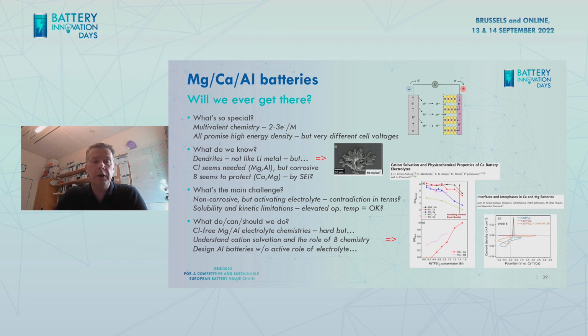One hobby horse of mine when it comes to aluminium batteries is that aluminium batteries is one thing, aluminium ion batteries is something else. So if you're going to use, let's say, graphite, where you intercalate AlCl4, for instance, then you actually take an active role of the electrolyte to form what actually is intercalated. And if you do that, you're never going to reach very high energy densities in practice. It might look nice, but you really have to calculate what it means to your cell design. So I think that designing aluminium batteries where you really have no active role of the electrolyte, and what does that mean? That means actually the Al3+ should be your active species.